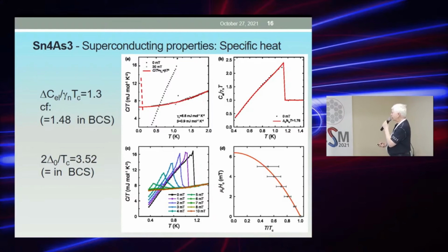Now we focus on the specific heat again. The temperature dependence of the specific heat shows a sharp drop, which can be analyzed, and lattice and phonon and electron contributions are separated. We again find that the amplitude of the specific heat gap is very close to that in the BCS theory. The temperature dependence on the magnetic field is also consistent with the BCS theory, and the 2 delta over Tc ratio just coincides with that in BCS.